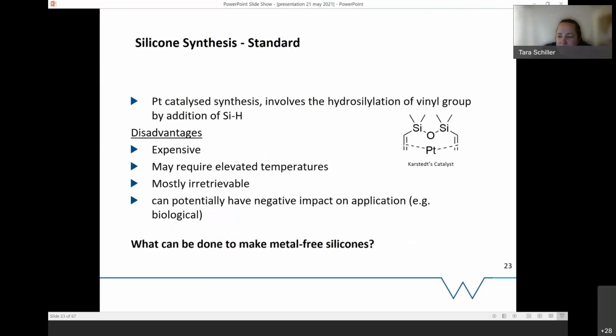If you buy a Dow Chemical silicone, it'll be a platinum catalyzed reaction. This is done at temperature. It's an expensive catalyst. Most of the time it's done at temperature, I should add. It does start curing at room temperature, but it's not that quick.